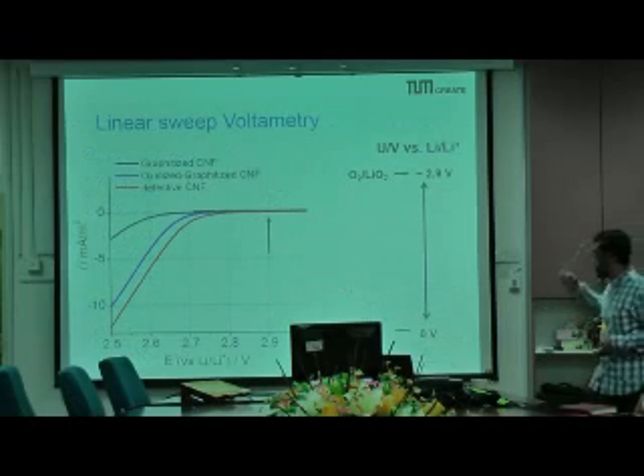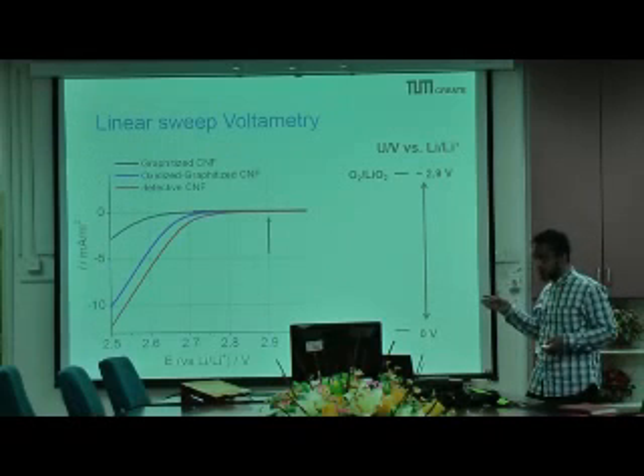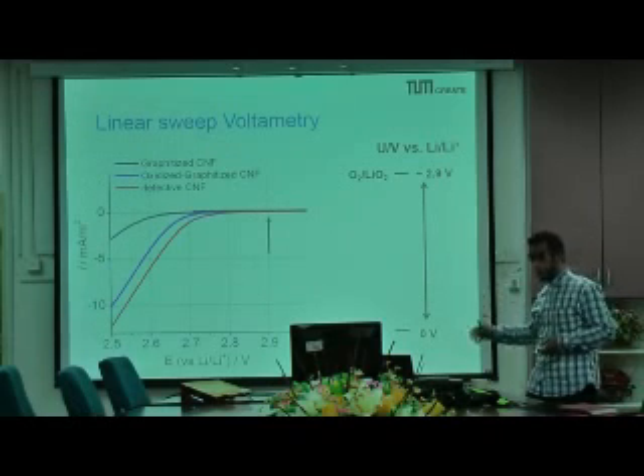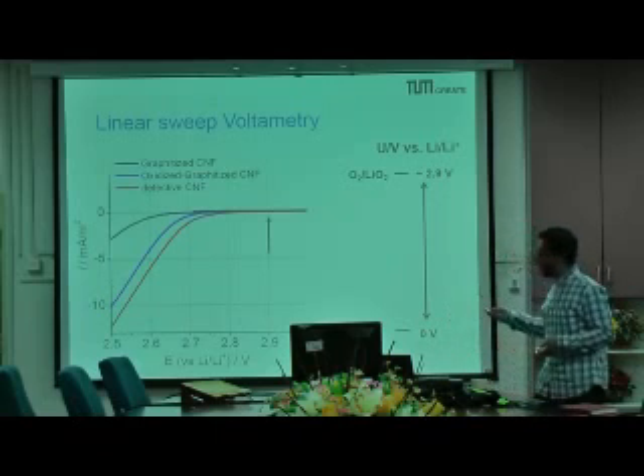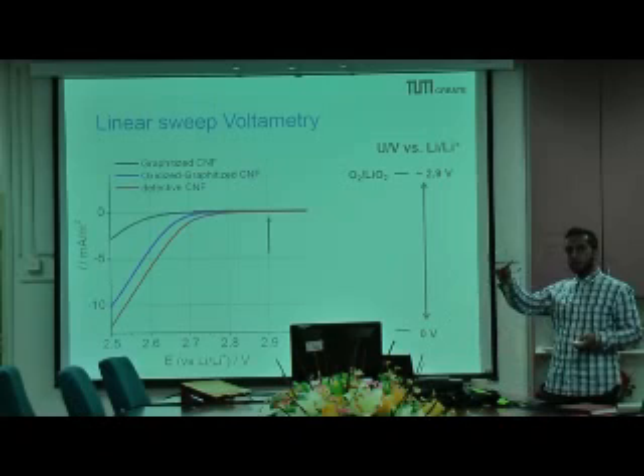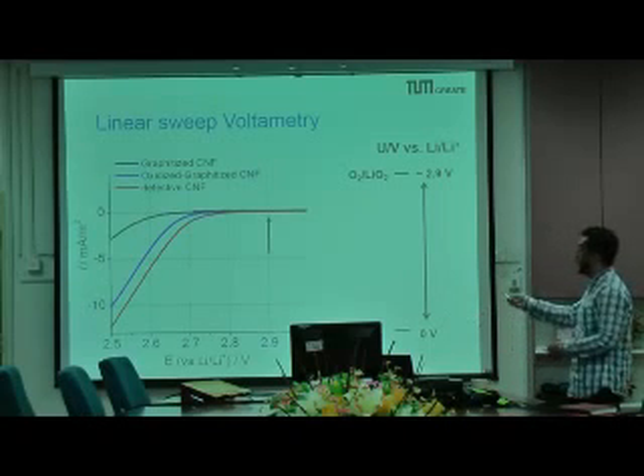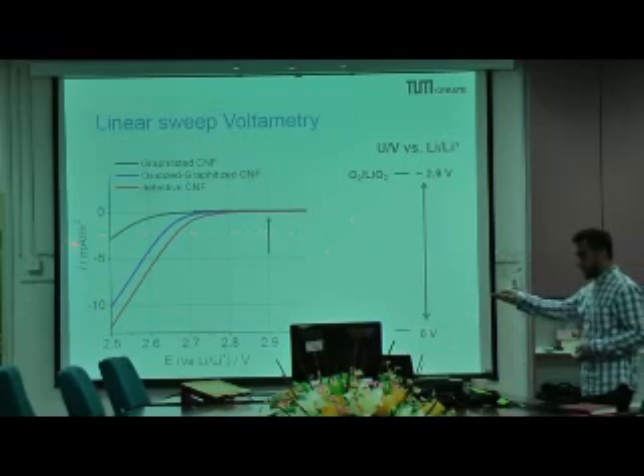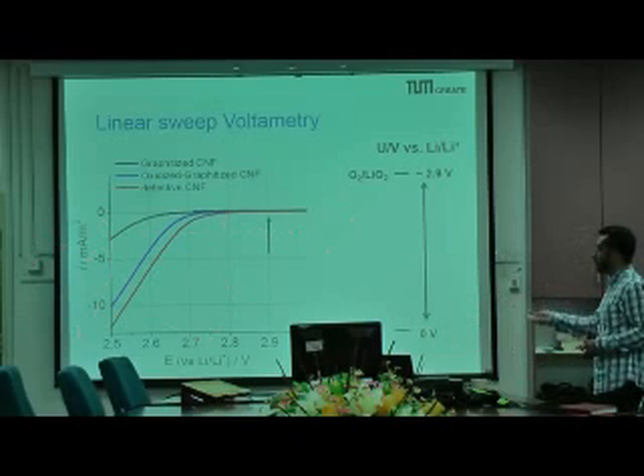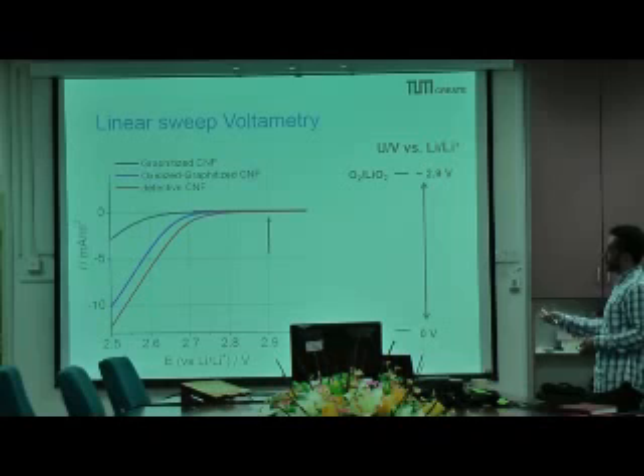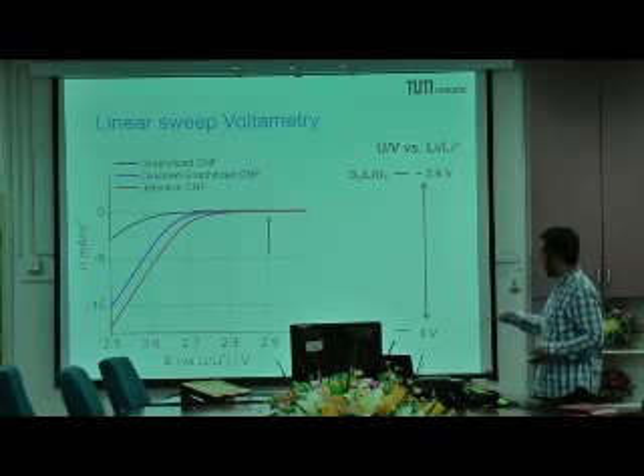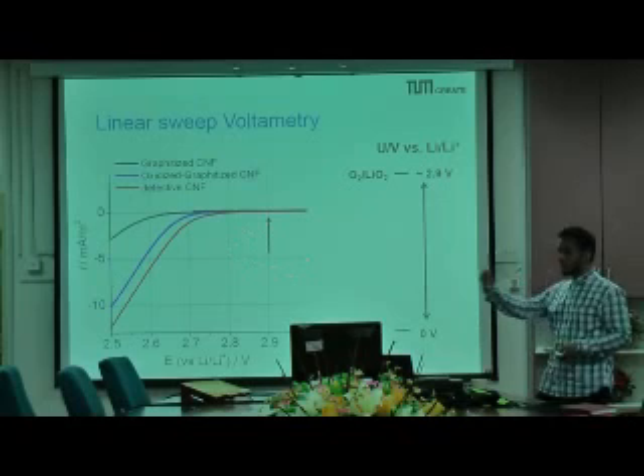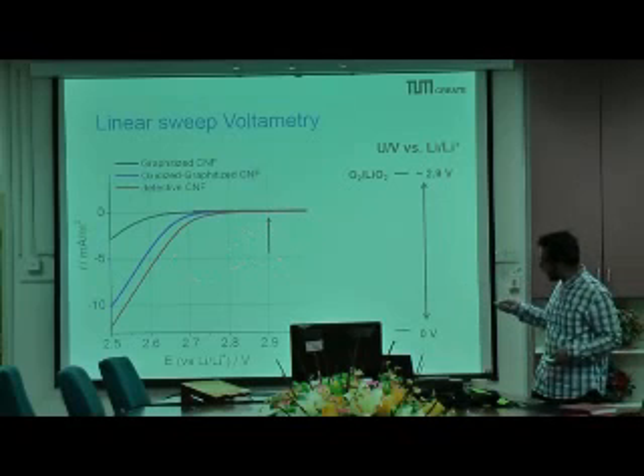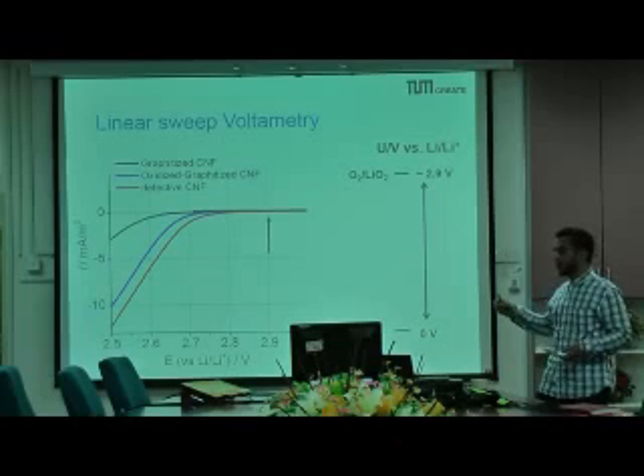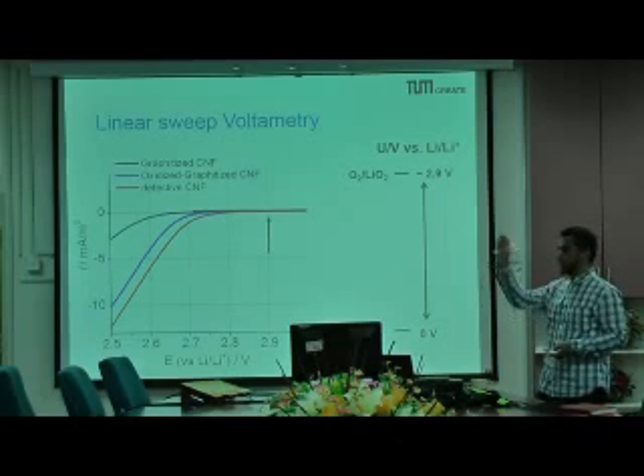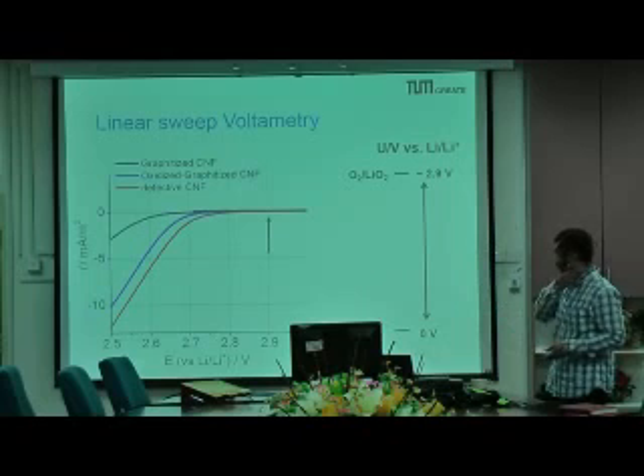This is a steady state experiment called linear sweep voltammetry. What it does is change the potential, or the energy level, of the cathode with the potentiostat, an instrument that you have, sweeping to lower potentials and seeing the current response of that variation. If the material is very good, once you move to the left side of high energy, you immediately start to see some current. If the material is very bad, you don't have that current until you go very low.